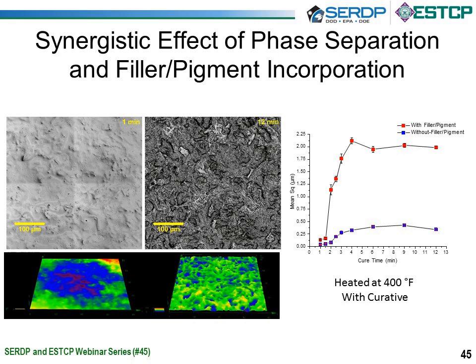we wanted to utilize the same technique as we did earlier with our ability to follow the reaction through roughness formation, this time with the addition of the pigments. On the left side is a continuous film on a surface at 1 minute cure, and on the right is the 12-minute cure. You can see that there's a dramatic difference in roughness. If we look on the graph on the right side, we see that the line at the bottom illustrates the earlier presented incompatible polymer system that has been cured and roughness analyzed without pigments, as compared to the line at the top, which is with the pigments and fillers.